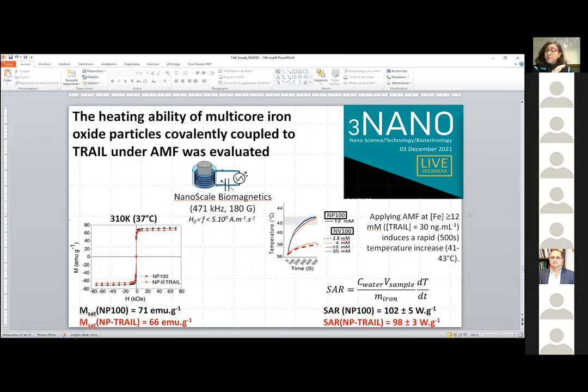And this increase is quite equivalent, you can see the plots here, for both the bare particles and the nano hybrid ones. We determined the specific absorption rate using the slope of the temperature as a function of time curves. And we obtained almost the same value, suggesting that the TRAIL coating has no effect on the heating. So we obtain a value around 100 watts per gram of iron.